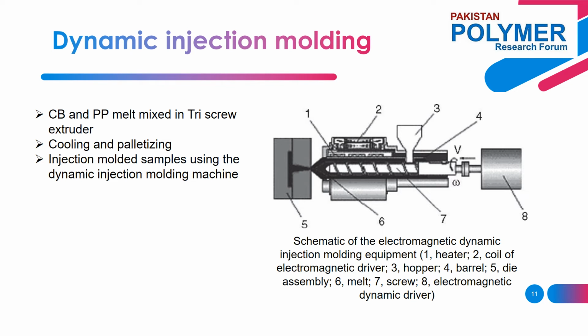In this research, carbon black was premixed with polypropylene pellets in a mixer for 10 minutes in various ratios, and then fed into the twin screw extruder operating at a screw speed of 90 rpm. The resulting extrudate was cooled in water and cut into pellets using a pelletizer. The extruded pellets were dried again in a vacuum oven. Standard samples were molded via a custom-made electromagnetic dynamic injection molding machine, as shown in the figure. Electromagnetic force applied vibration with different frequencies to study the effect of electromagnetic vibration forces.